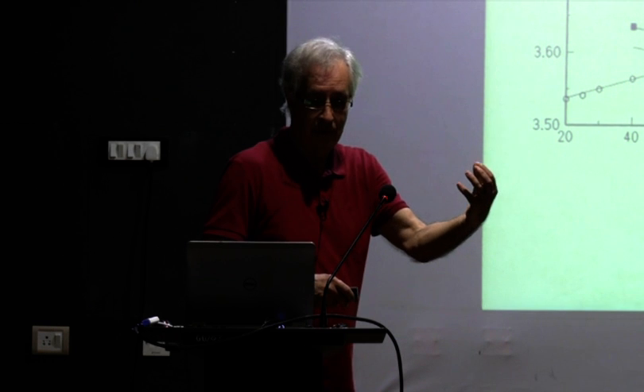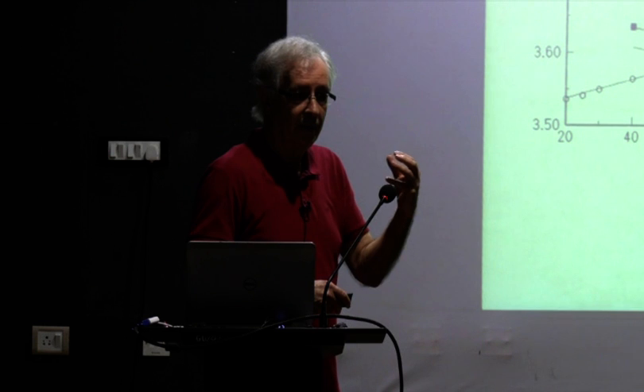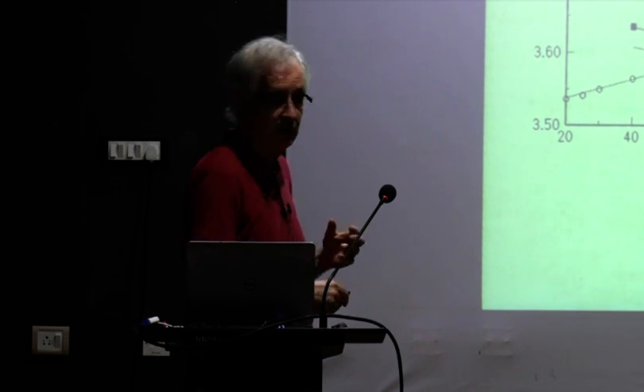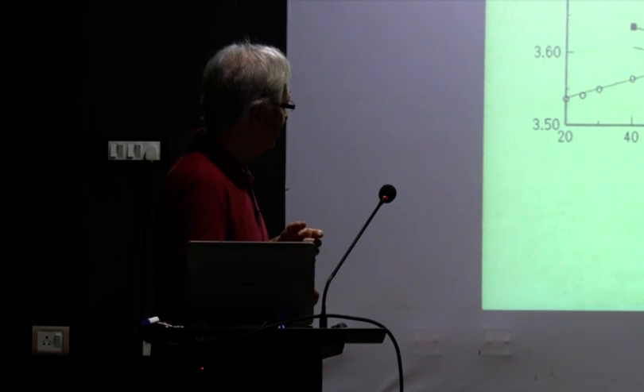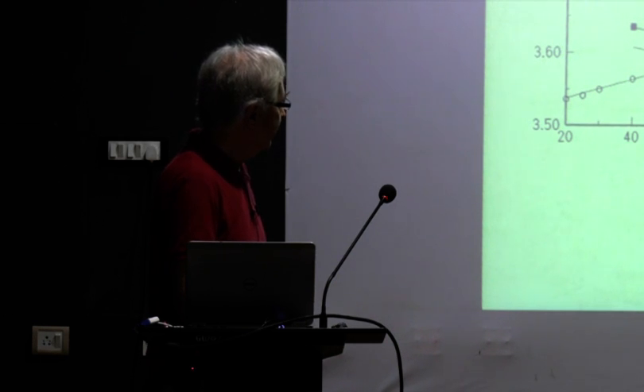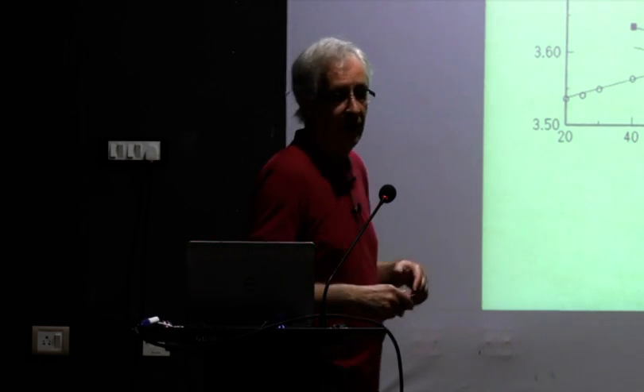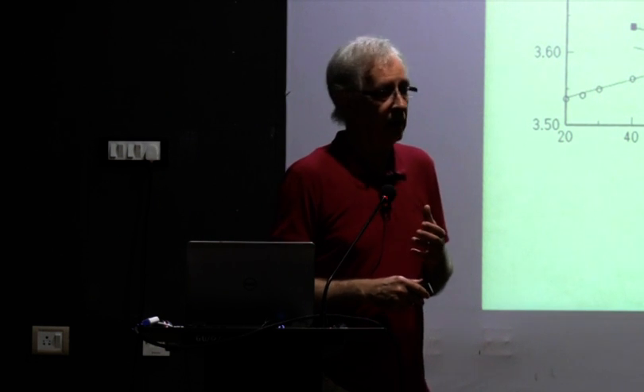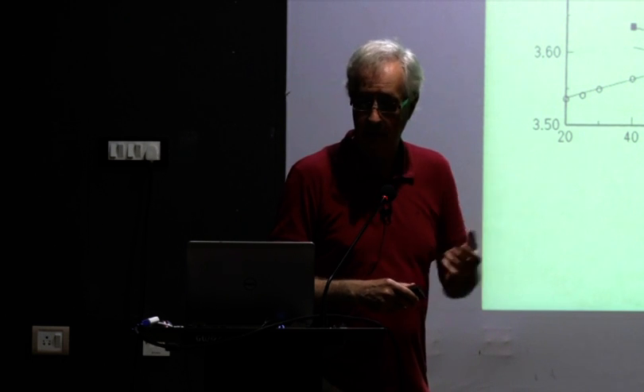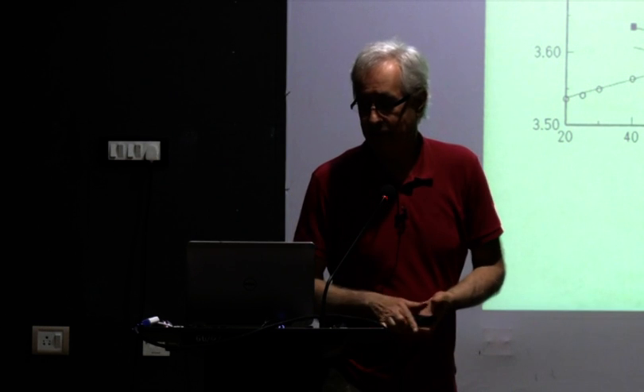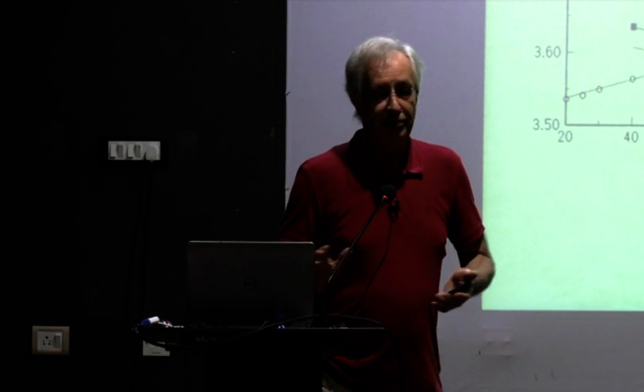So you have a volume which is stabilized at a higher volume than for the antiferromagnetic materials when it's extrapolated from the antiferromagnetic materials. So in this case, Fcc iron has a low volume state, and here it has a high volume state. If you look at this deviation, and with some fantasy, you can perhaps say that, okay, as of the INVAR composition, it is going down again. So as you approach iron, it behaves more like the antiferromagnetic side, and you come to these 2 points. This was the first recognition that iron could come in two states depending on which environment the Fcc iron was. This was the simplest evidence.